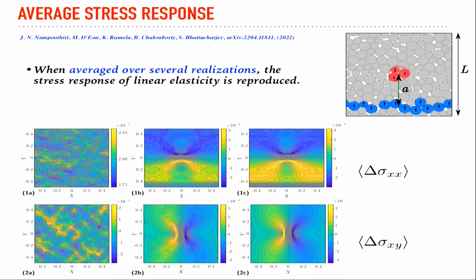So one way to do such a thing, to understand stress propagation in granular systems, is through doing a disorder average. What I mean by that is, in statistical mechanics, you always take an average over a configuration space or some time average quantities and so on. Well, you can do something very similar in granular systems. Here I've created a granular packing where you put some external forces at the center. Here, these three particles have an external force pointing downwards. So you're sort of pinching this configuration, and these are elastic particles, you could think of them as harmonically interacting particles. And you sort of counterbalance that force at the bottom here by adding forces on all of the particles along this line.